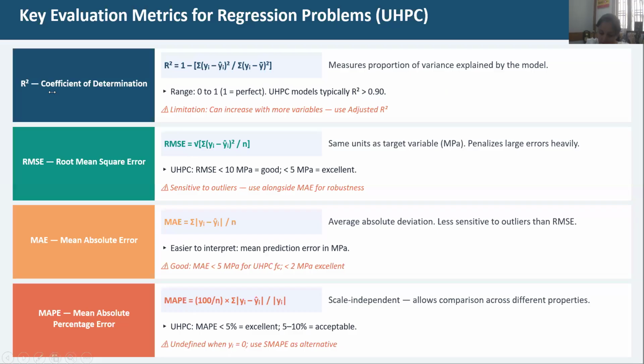So mostly we'll report the data with respect to R square, then RMSE, MAE, or MAPE, because when you have R square value close to 1, obviously it is impossible to get 1. So the typical range will be 0 to 1. It is impossible to get 1. But if you are reporting the R square coefficient as 1, that tells that the research is not valid, because no data will give you 100% of results. So typically your R square values can be somewhere in and around 0.9 or 0.85, that range. Even 0.95 or anything greater than 0.95 of R square value is not typically considered, because you might have overseen the data, or you might have overfitting or underfitting, which is again not a standard way of reporting the data. So keep that in mind when you are going with evaluation metrics also.